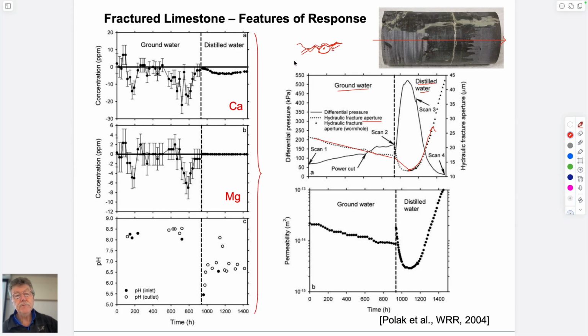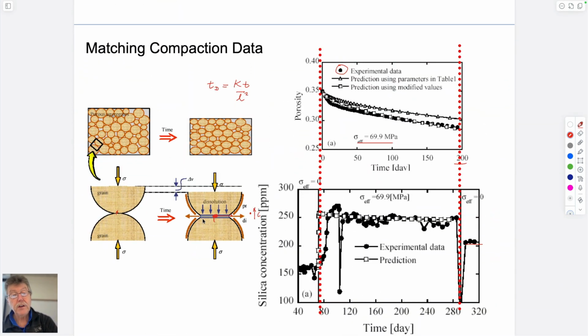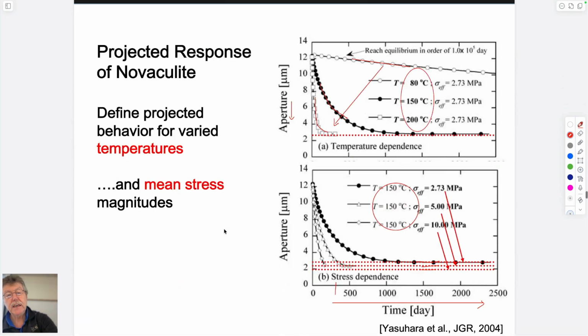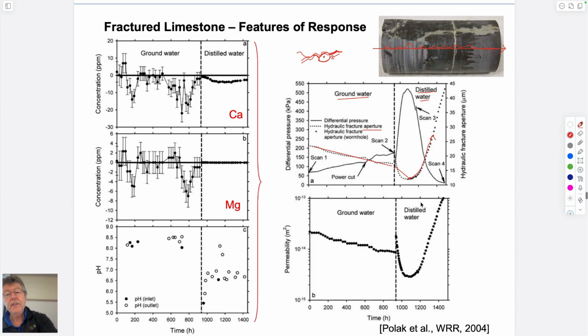But once you get to a certain closure, then the rate at which pressure solution can transport dissolved components on a longer anvil. So you remember the contact goes from a short contact to a very long contact. As it gets longer, the efficiency of ejecting mass into the pore fluid decreases, and at that stage, free face dissolution on this conduit starts to grow. And as a result, if this grows and this pressure solution is swamped by this behavior, all of a sudden you get a wormhole developing its way all the way through from upstream to downstream. And that's exactly what it was. You get a single conduit down the middle of the sample as quite literally a wormhole.